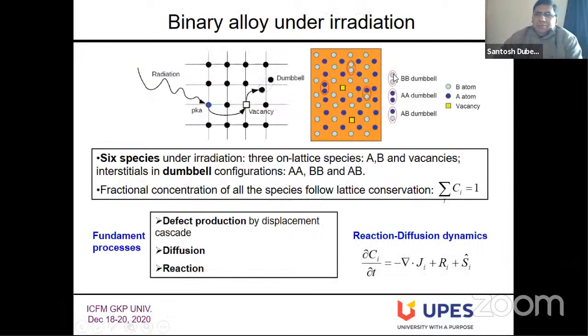I'm just giving an example of a binary alloy case, an AB kind of system, which under irradiation can have several species. Considering that A and B atoms are of similar size, you can have A and B atoms, you have vacancies, and you can have several kinds of interstitials. In my case, because the A and B species are of similar size, they will have dumbbell type interstitials. So you can have pure interstitials. You can have mixed interstitials.